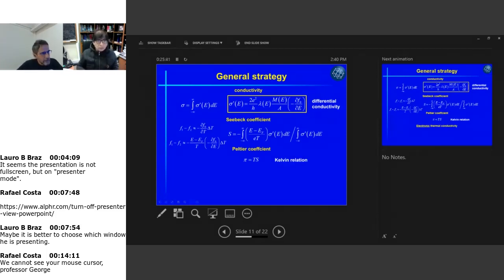This is the so-called Kelvin relation, and this is a universal relation because it can be proven using thermodynamic arguments. But then I would get exactly this expression here, but this T would not be showing up in the expression for the Seebeck coefficient. And then the electronic thermal conductivity is given by this expression. Again, it is very similar to the other three expressions above. The difference is that now E minus EF is raised to a square. I have the square of E minus EF.